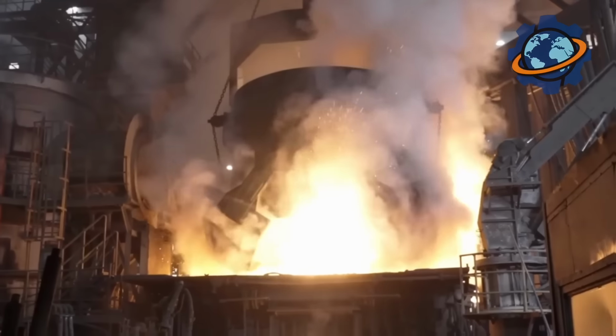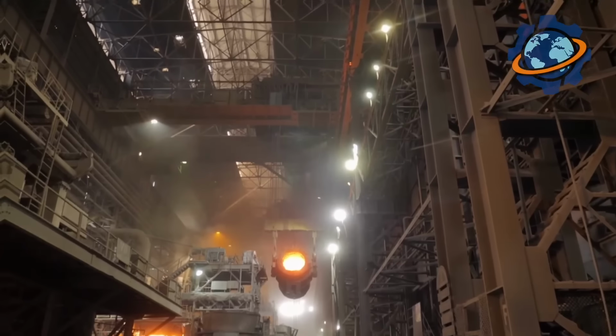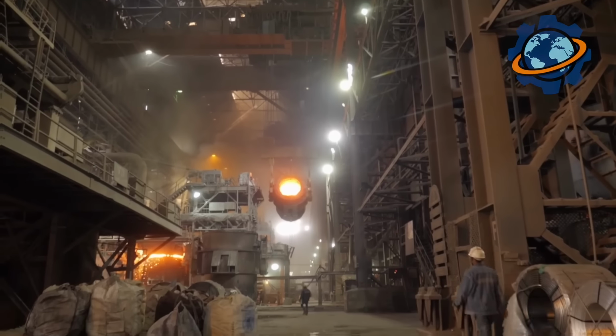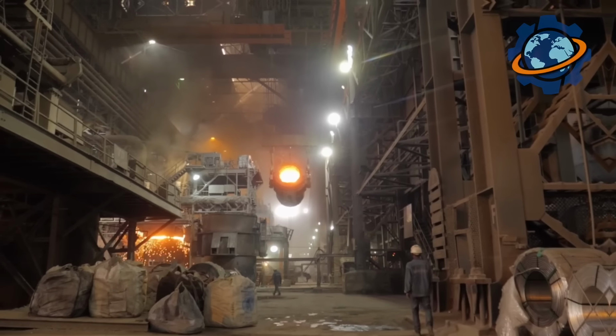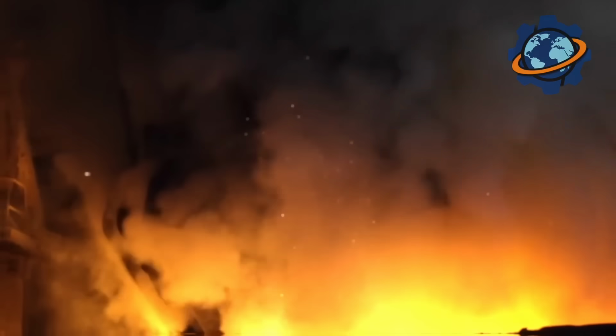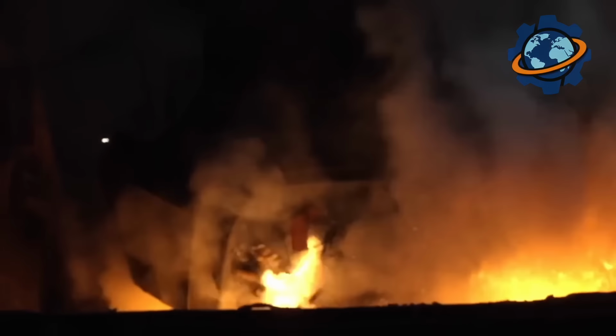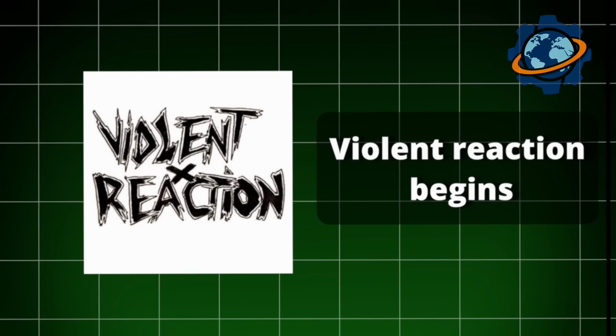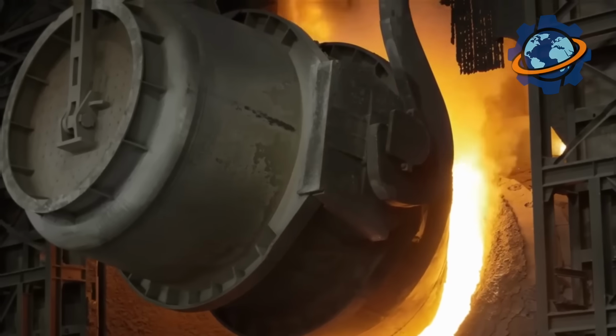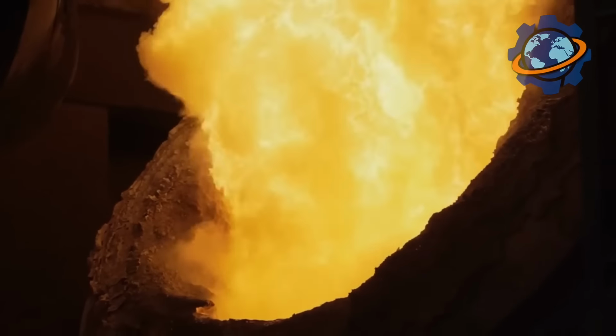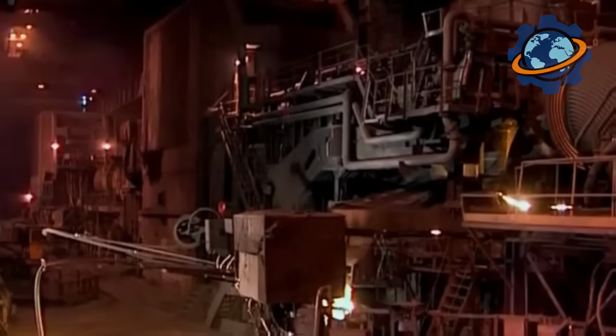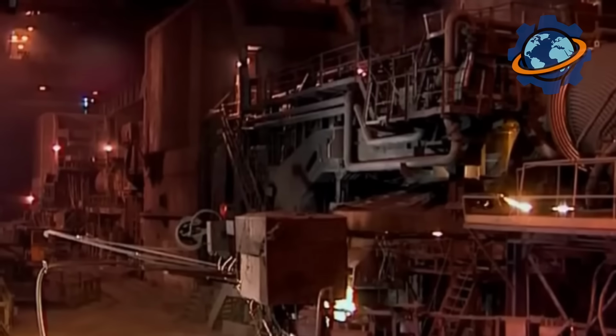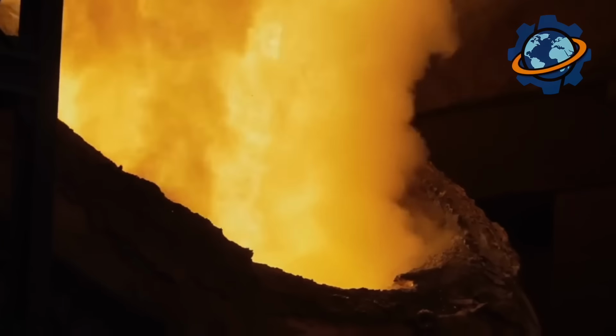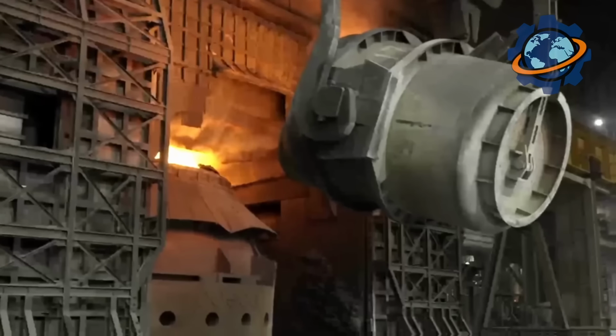An oxygen lance, a tube 20 inches in diameter, lowers from above. Oxygen flow begins. A jet of pure oxygen at 150 pounds per square inch pressure strikes the molten metal. Violent reaction begins. Oxygen oxidizes carbon, silicon, manganese, impurities in pig iron. These exothermic reactions release enormous heat. Temperature rockets to 3,200 degrees Fahrenheit. Metal boils and churns.